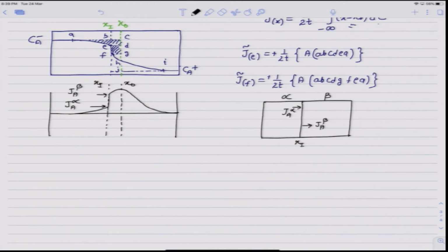We can similarly draw various types of flux profiles, which I will give you in the exercises. Now, the question is, how do we use this data? Once we evaluate the diffusion flux profile, how can we make use of it? Obviously, with the multiphase diffusion couple, using the same approach as for single phase couples, we can also determine the interdiffusion coefficients. For binary, a single couple would be okay for determining interdiffusion coefficients at different compositions. For ternary, we will need two couples with intersecting diffusion paths and so on.